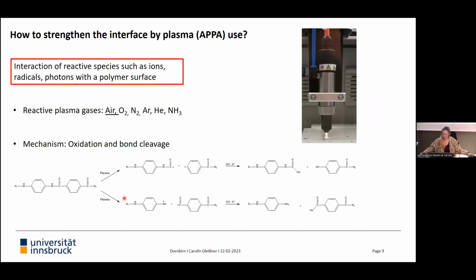And here's just a possible mechanism. So what can occur when the plasma is interacting with, for instance, an aramid. There can be a cleavage between the amide group and the phenyl ring here. As a result, radicals can be formed, and when they interact with protons or hydroxyl groups, for instance, here a carboxyl group is formed or a hydroxyl group is formed. There's also the option that a cleavage within the amide group occurs. Again, radicals are formed, and if they are interacting with other reactive species, then also here a carboxyl group is formed, and an amine group is formed. So in general, you can say that new functional groups are formed.